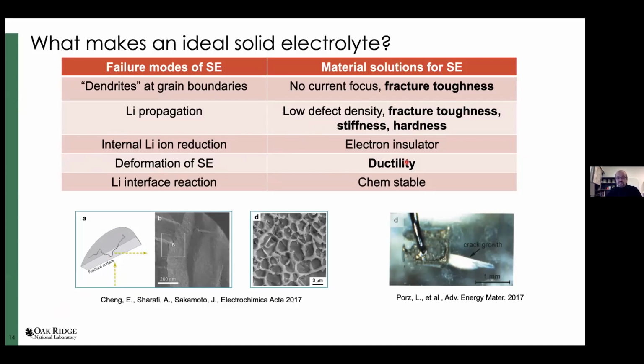So it needs to be ductile enough so that it can deform together with the cathode particles without losing the contact. Yet it needs to be stiff enough and have high fracture toughness to prevent lithium from penetration. It needs to have high hardness as well. So some of these things on this list are almost contradictory to each other, because most materials, if they have high hardness, are also brittle. But as I will show, there are some ways to introduce some ductility into these materials.